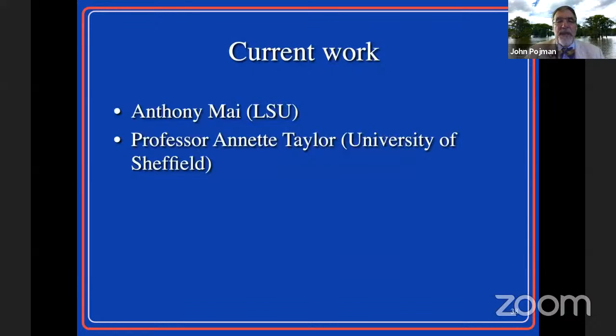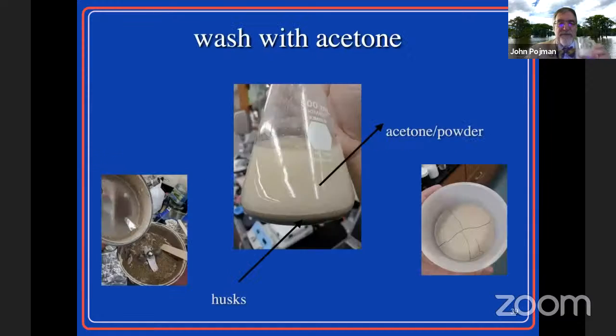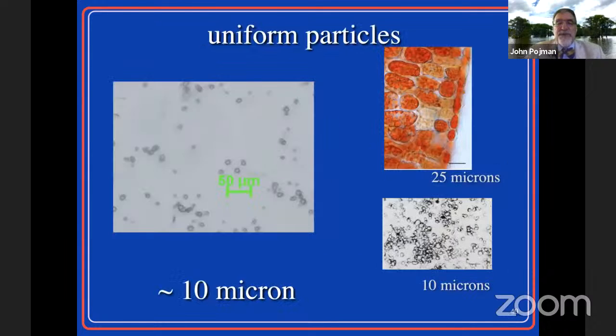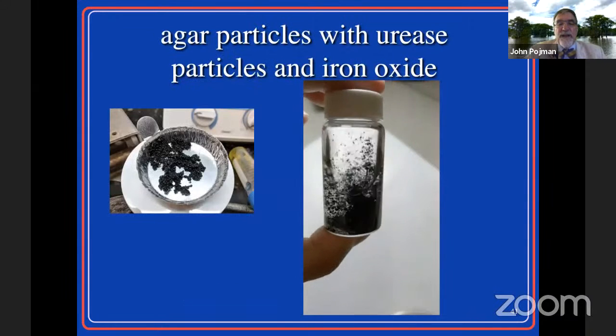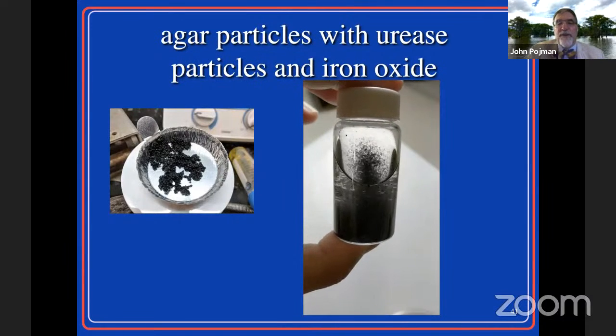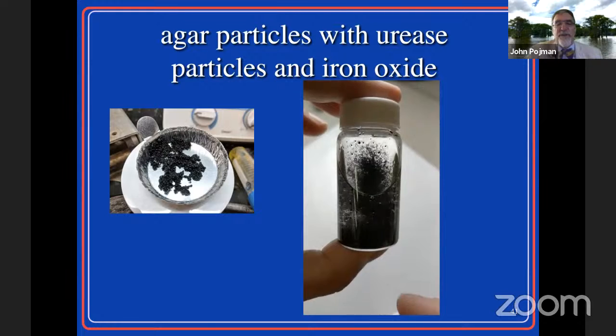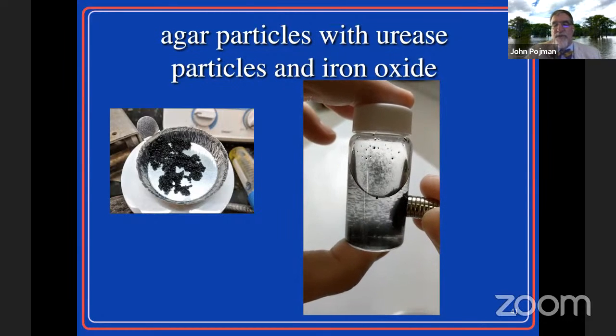We're working currently with a brilliant student, Anthony Mai, and with my good friend and collaborator, Professor Taylor at the University of Sheffield. Anthony found that by taking watermelon seed powder and washing with acetone, he could get a pretty much monodisperse system of particles. We don't really understand exactly what these particles are. They seem to be some kind of protein body, rich in urease and possibly other enzymes. Anthony put those inside agar particles, a naturally occurring gel, with iron oxide, and he can move them around with a magnet.